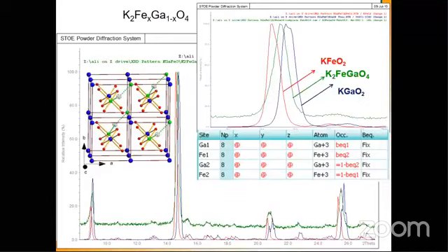How XRD shows these changes. Quick two slides and then I will finish maybe. For example, you are putting gallium into iron. Whether it has hit the proper atomic site or not, you have to see the shift in the diffractogram. You have KFeO2, which is red. You have potassium gallium oxide, which is black. So green is the potassium ferrite doped with gallium, which lies exactly in between the two.